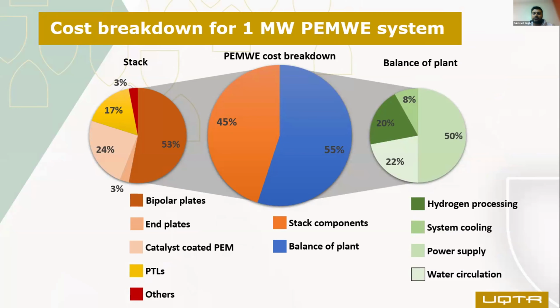Now, if we see the individual cost of these components, 55% of cost goes to the balance of plant, which includes hydrogen processing, system cooling, power supply, and water circulation. And almost 45% of the cost comes under the stack cost. And if we further break down the stack cost, a major cost goes to the metallic components, surprisingly not the precious catalysts, compared to other electrolyzers. Catalyst takes almost 25% of cost, and in the next slide we will see how 70% of the cost goes to only two metallic components, which are bipolar plates and the PTLs.